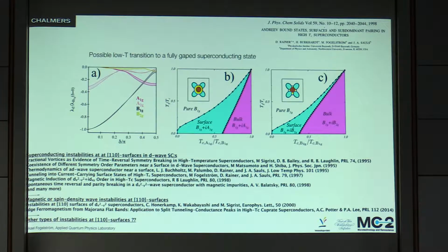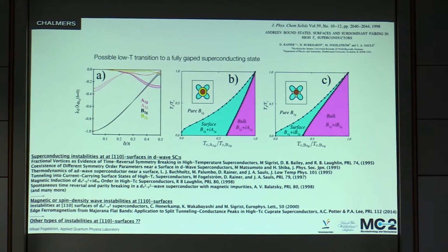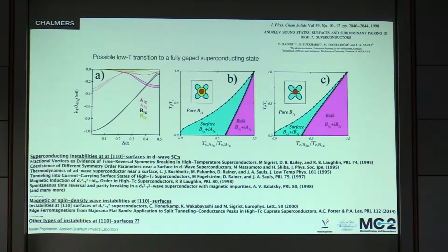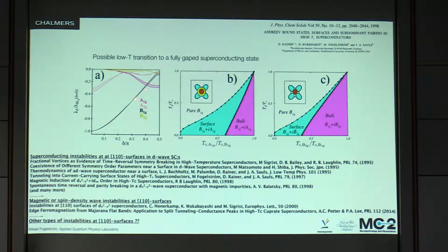Let me adjust the picture here a little bit. Okay, I'll bring it a little bit closer. Now, if you have any residual interaction, and these are just pairing strengths as a function of some spin fluctuation model, you see that not only the D-wave pairing interaction is attractive, but also a subdominant one exists. And just due to this large number of states at the Fermi surface, you just need an infinitesimal pairing strength to actually generate a surface state.